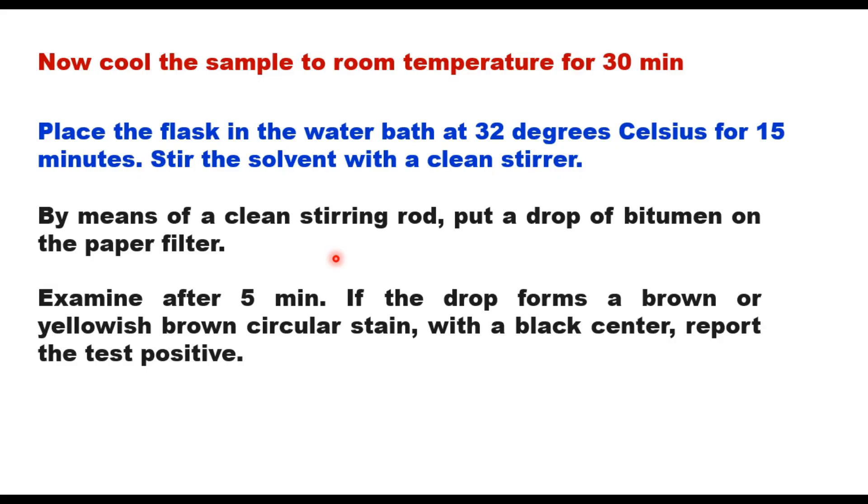Examine after 5 minutes. If the drop forms a brown or yellowish brown circular stain with a black center, then the test is positive.